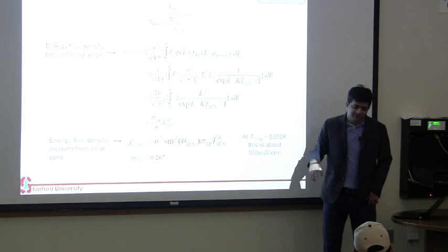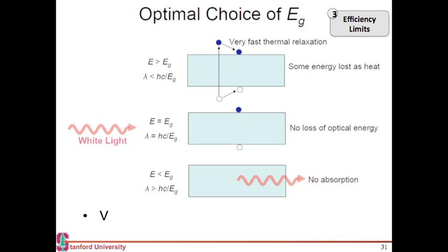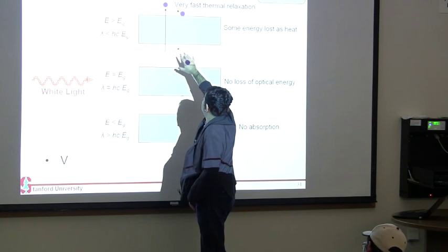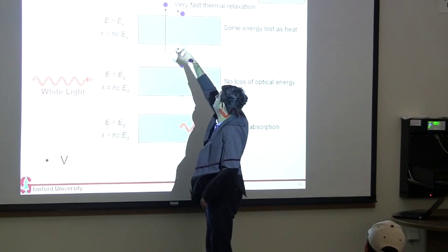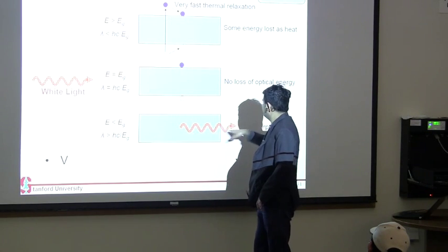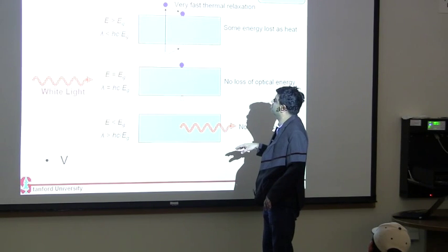And then what I need to do is figure out how much energy I can get out of it. So I need to integrate my solar spectrum over my band gap. Whenever I have light coming in at a given energy, if it's higher than the energy of my band gap, then I'll lose that extra energy as thermalization, because these carriers will thermalize before I extract them. Although there are some people trying to extract these hot electrons as a way to increase the efficiency of the solar cell, assuming that technology is not out there at the moment, these carriers will thermalize and you lose that extra energy. If the photon energy is less than the band gap of that material, I'll lose the photon as is. I won't be able to absorb it at all.